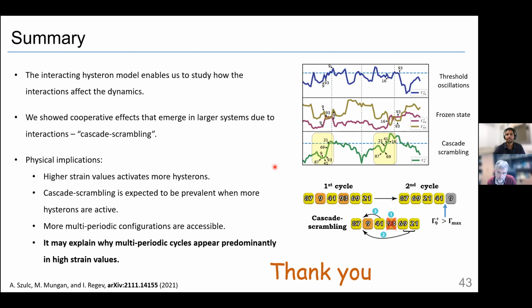So at every strain, you have soft spots at certain strains, and you could have them accumulate close by in strain. Density in strain is what I meant, not in space. I didn't check how many soft spots I have in each strain, but you can see that for lower strain values, you get mostly period-one cycles. When you increase the strain, you increase the number of hysterons, and you can see the multiperiodicity. The relation is somewhat linear. When you increase the strain value, the number of active hysterons increases linearly. I see. But I don't have the exact numbers.